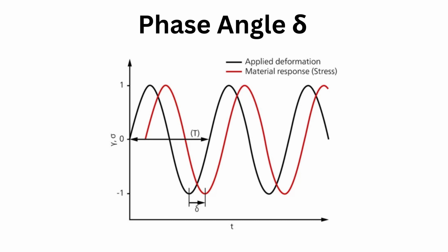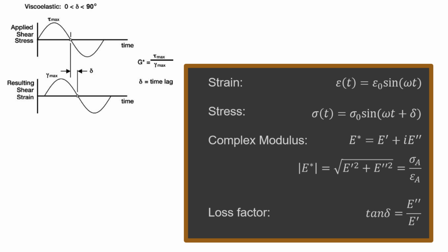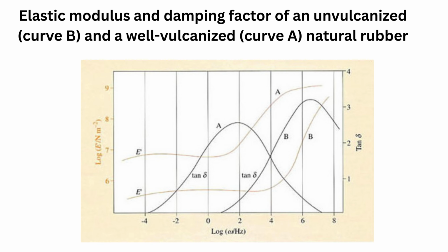From the definitions of the dynamic moduli and by manipulation of the linear relationship between the sinusoidal stress and the corresponding strain response, the phase angle delta can be expressed as follows. Tan delta equals E double prime divided by E prime. Tan delta is commonly called the loss tangent or damping factor. E prime and tan delta are the most commonly measured dynamic properties of rubbers, representing the elastic stiffness and damping or hysteresis properties respectively.